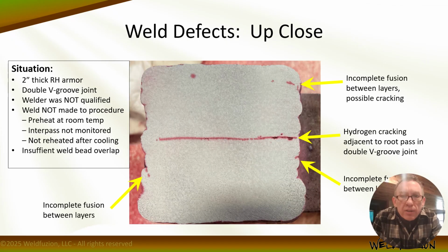Let's take a look at this application. The material is 2-inch thick, RHA, rolled homogeneous armor set up in a double V-groove joint. Note the incomplete fusion and cracks that were found upon sectioning and running some penetrant testing. Upon further inspection, it was noted that the welder was not qualified and the weld was not made to procedure.